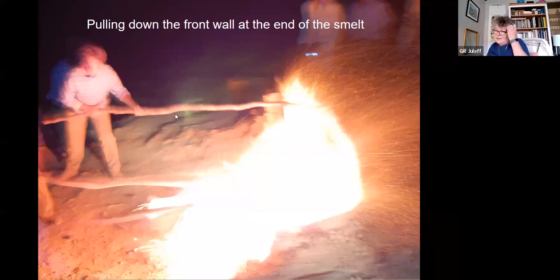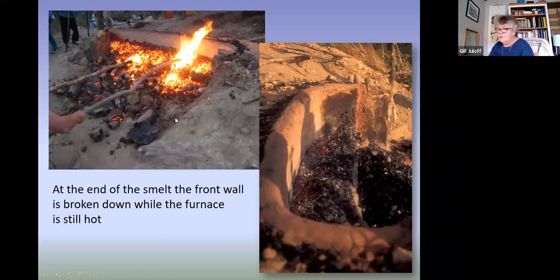It's very, very hot. You can only do it at a great distance with a 6-foot wooden pole. It takes a lot of effort. And this is the sort of mess that gets made. And this is our furnace soon after the smelt is completed. What's really exciting about this is that we see this line of tuyeres here. The front wall has all collapsed. We see the damage in the corner of the furnace. We see the relative lack of burning on the back wall of the furnace. So this looks very like our archaeological furnaces.